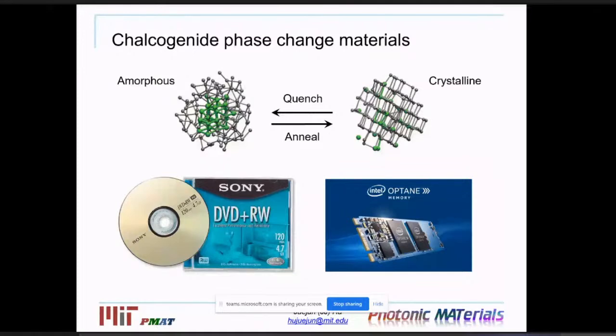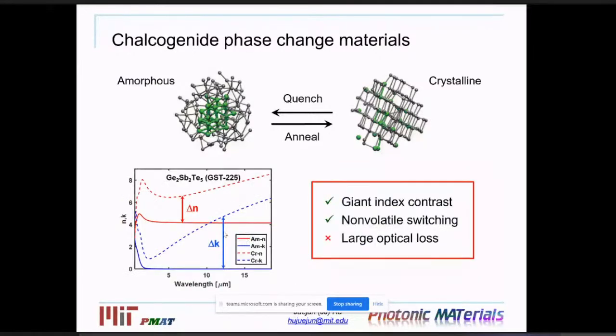And the biggest challenge there is that these conventional materials, if we look at optical properties, especially in the crystalline state, have very strong optical absorption that comes from free carrier absorption. That makes this material optically opaque in the infrared. And this makes any kind of optical application quite challenging just because of this very large optical absorption.